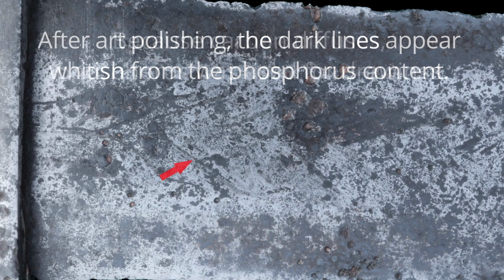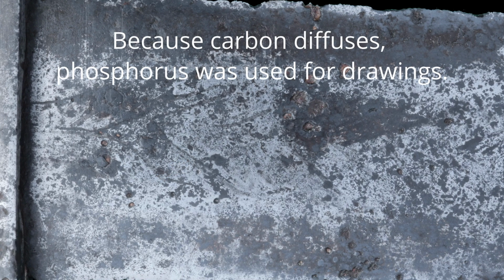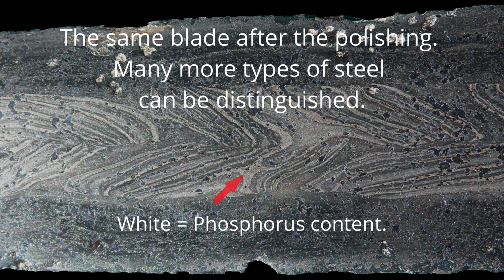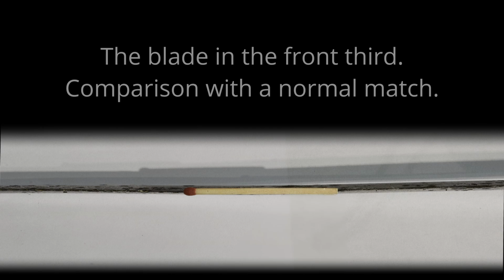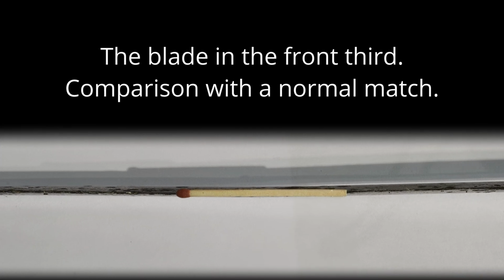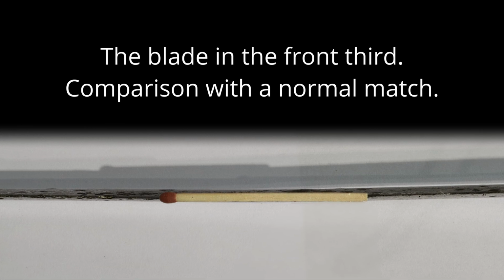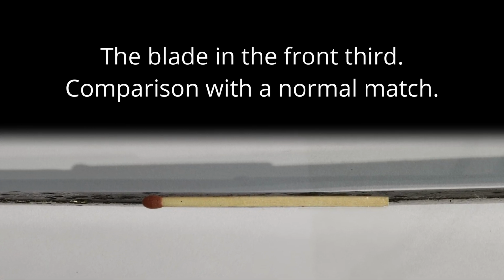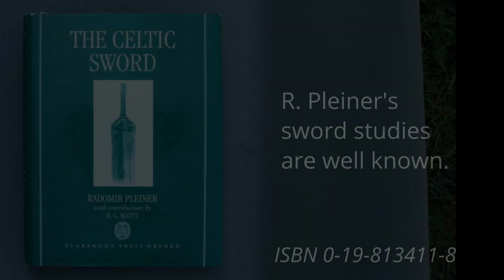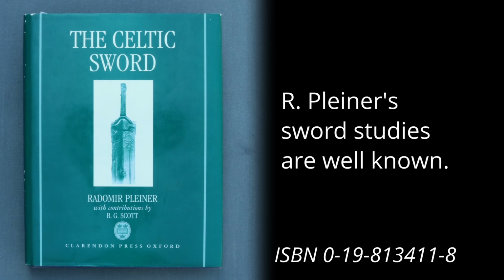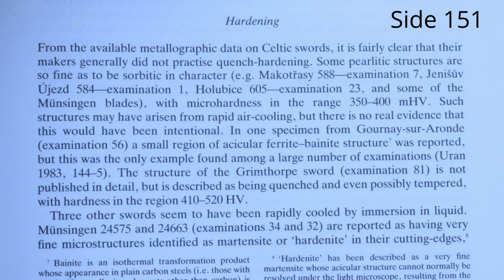What is amazing is that the blade is not hardened. This means that this blade is actually only slightly harder than copper. Like many such blades, it is only a very thin blade, about 4.5 millimeters thick at the root, tapering to 2 millimeters at the tip. This is not an isolated finding. From the beginning of the Iron Age, for around 2,000 years, many swords in Europe were not hardened with carbon. This is still one of the unsolved mysteries today.